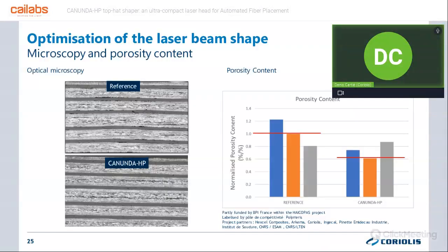Then we also had the opportunity to work on the beam shape and beam dimensions to optimize the health of the material. The main advantage of thermoplastic processing is that if you do it in conditions which are called in situ, you can manufacture the part, and after the layup, the part is nearly finished, except for a few operations such as trimming or drilling. To do that, you need to optimize your process parameters to get a good laminate quality, and using the opportunity of the development of new optics, we worked on the dimensions of the laser beam, and we can see on these slides that thanks to that we managed to reduce the porosity content by changing the laser beam shape.